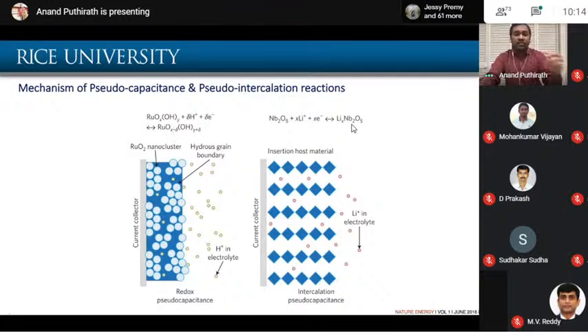At the surface, if you have a high atomic number, ruthenium oxide-like structures, the outer electron configuration has a nucleus, but since they are big enough, the crosstalk between the outermost electron and the core nucleus is slightly lower or very much screened, so there are chances this system can partially oxidize and reduce on the surface even without the total charge transfer. We used to say partial transfers, so that you will have an electrical double layer plus charge transfer resistance.